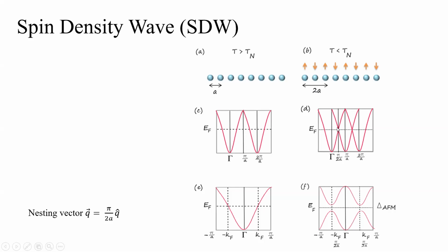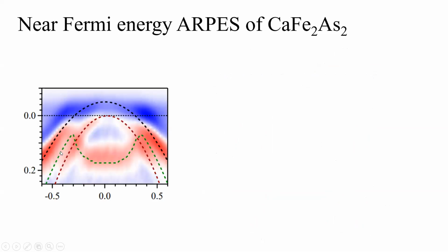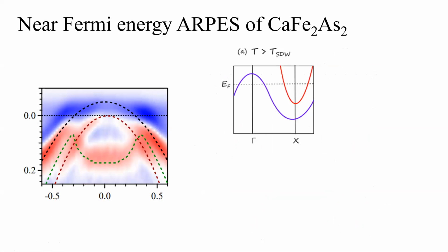And since these bands are crossing at these energy values, the lattice potential will create a gap at this energy. Now if I zoom in from minus pi by a to pi by a only, meaning within the first Brillouin zone, above TN it was like this, and below TN I will see this type of feature. So this is the reason why we see a back band folding in the case of CaFe2As2.